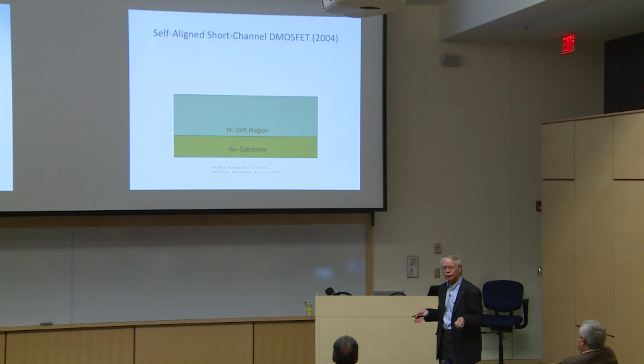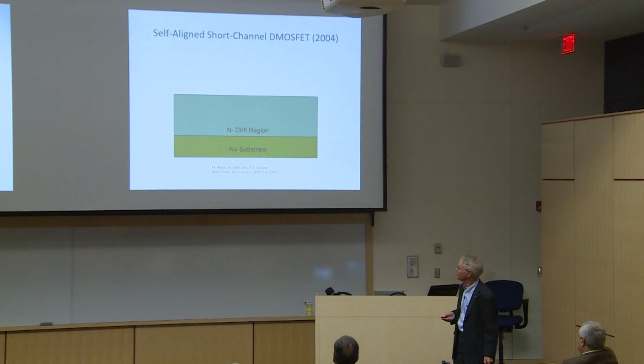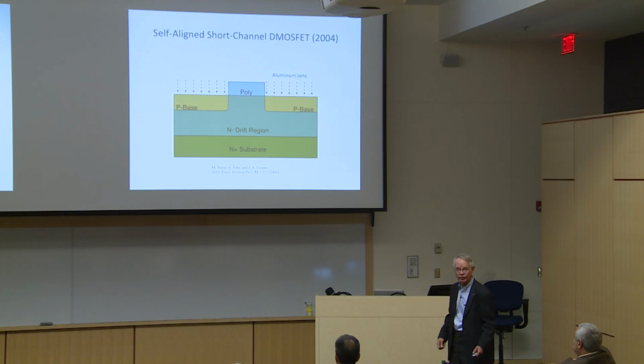And earlier we'd used metal masks and then stripped it off and then gone back and done the next implant. In the new process, we use a polysilicon mask. So we grow a thick polysilicon layer here and we pattern it. And this is going to be the implant mask. We then implant aluminum, which is our P-type dopant, and it's blocked. It doesn't go in where the polysilicon is.